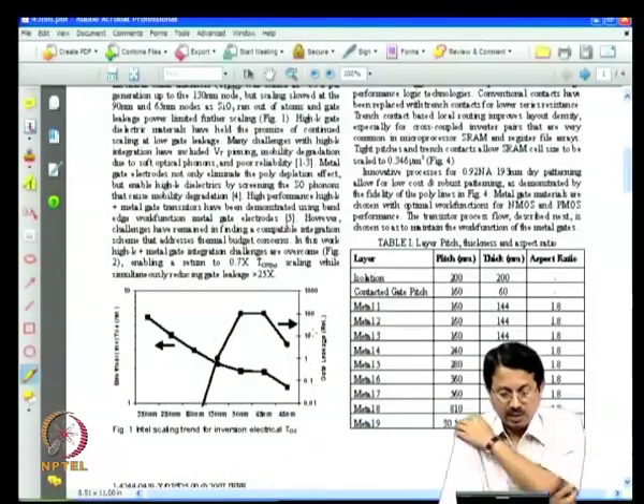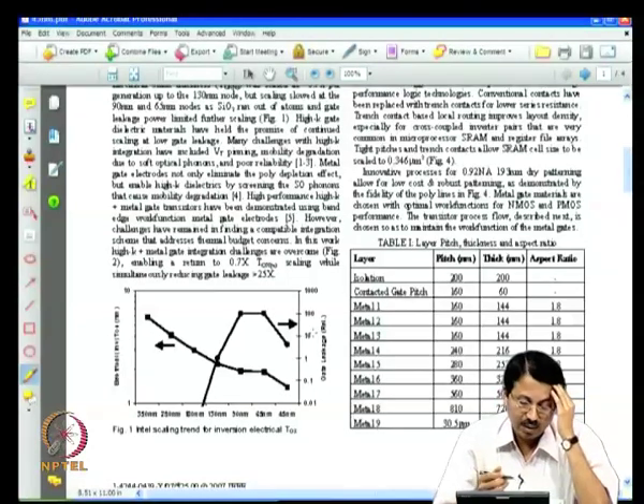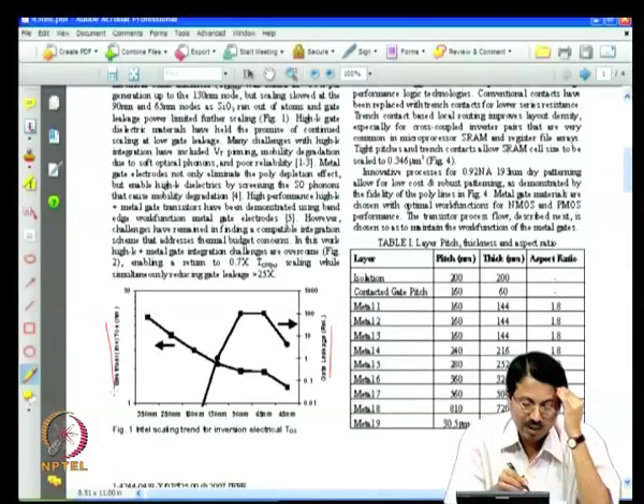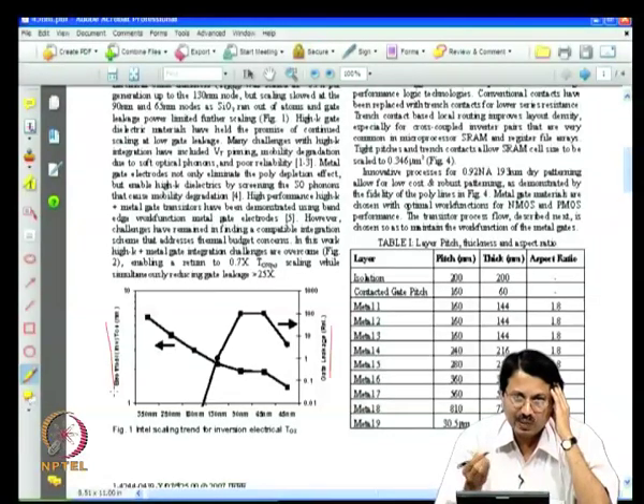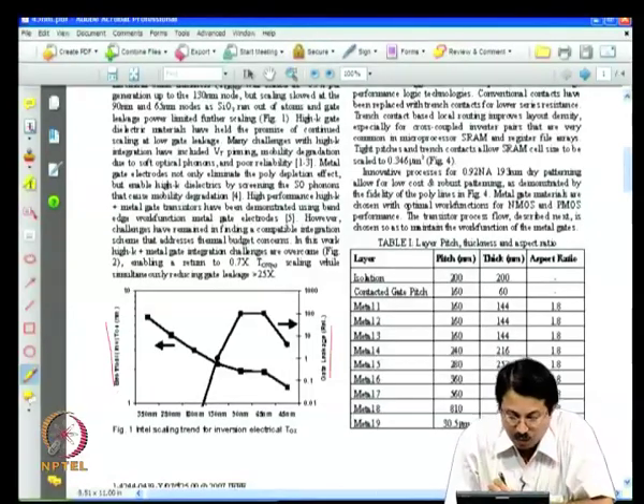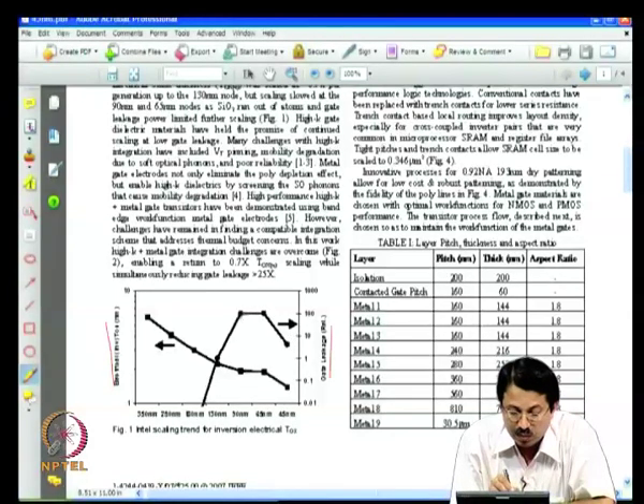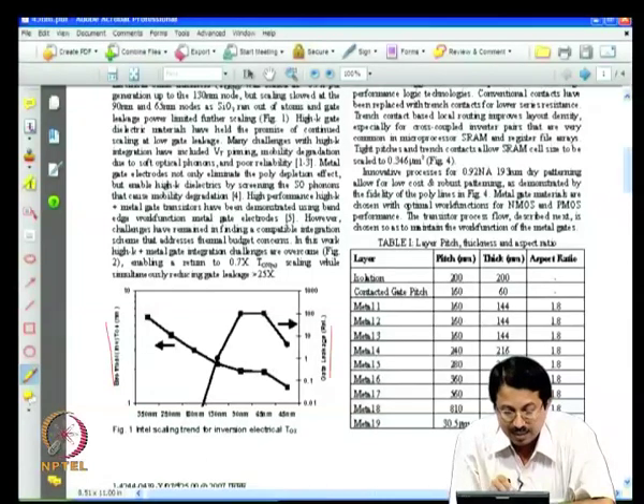So what they have been able to show here is the following. This is gate leakage, and this is oxide thickness, EOT. When you use SiO2, EOT and SiO2 thickness are one and the same. This is the 45 nanometer generation. At the 65 nanometer generation they were not able to scale the gate oxide thickness, because as we started decreasing the gate oxide thickness, leakage current suddenly started increasing because of direct tunneling current. And because from 90 nanometer to 65 nanometer they did not have a mature high K gate dielectric technology, they could not scale the oxide thickness. They kept the oxide thickness as is, and the leakage current stayed at the same level.